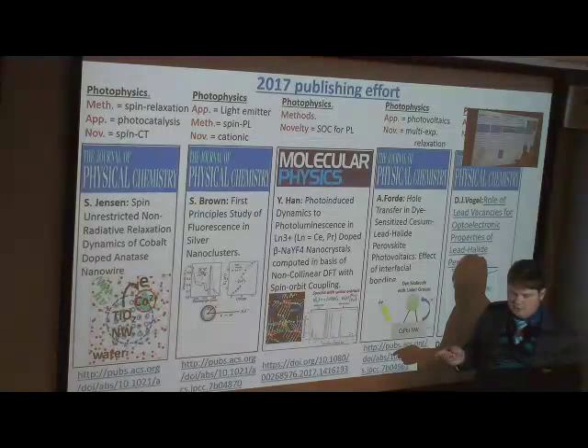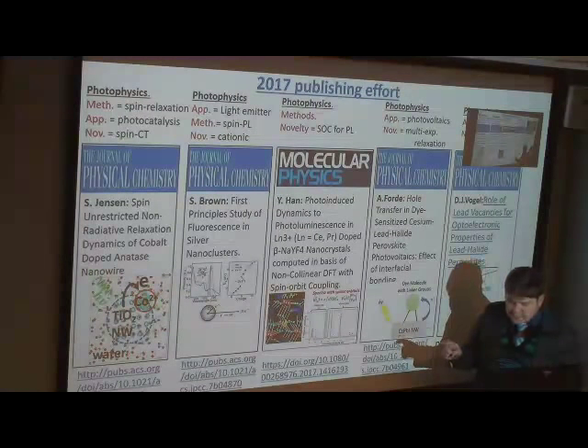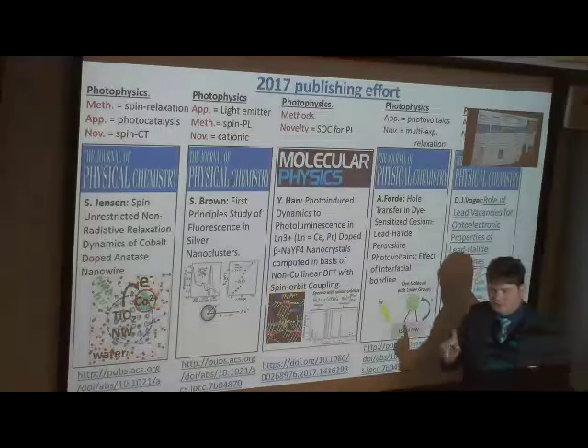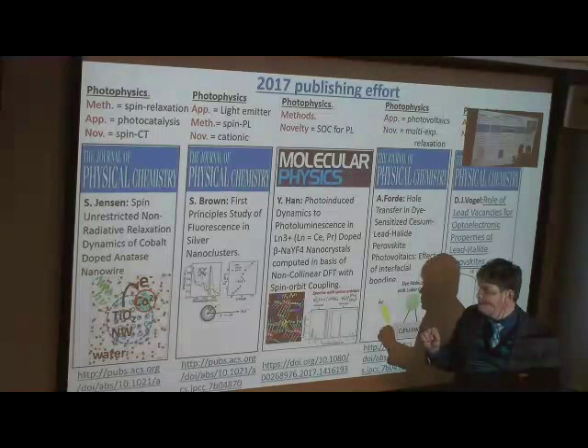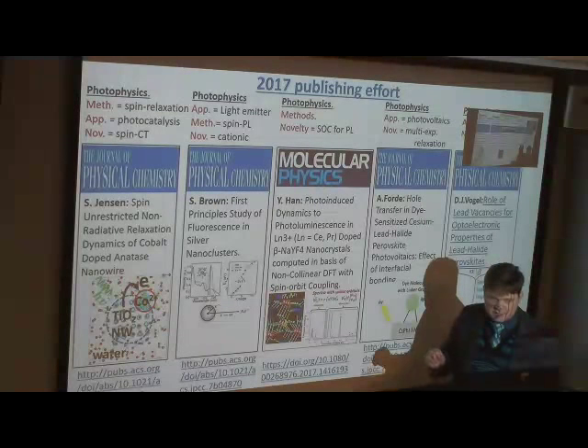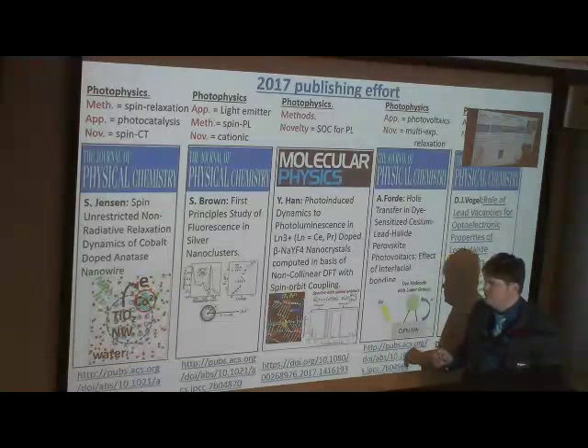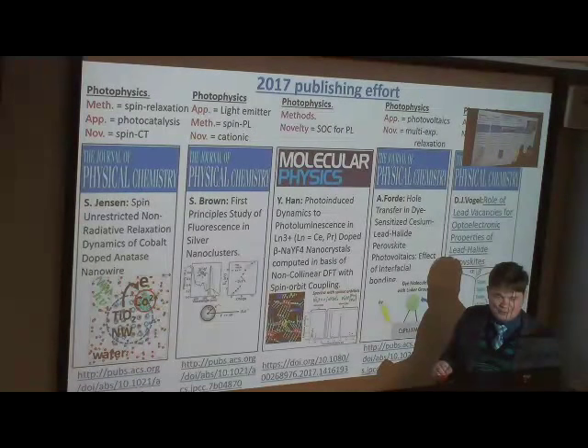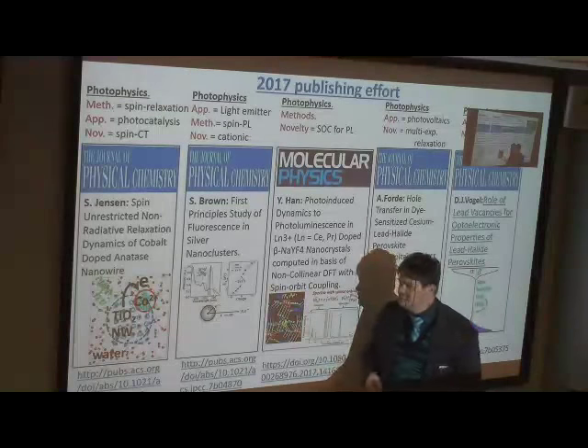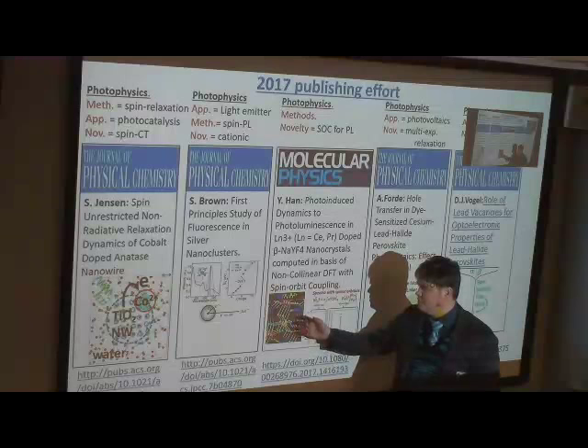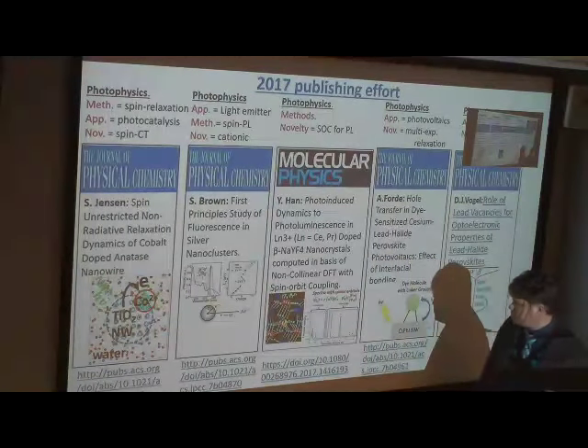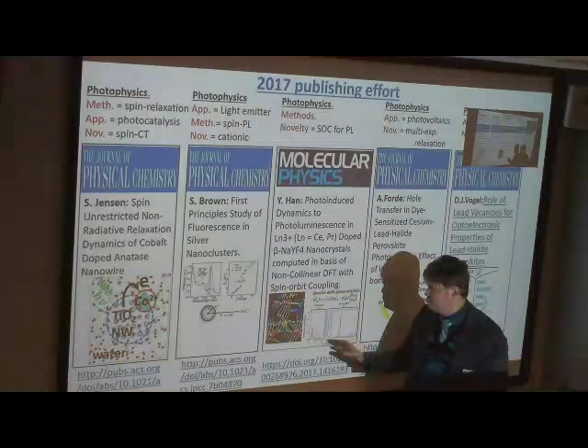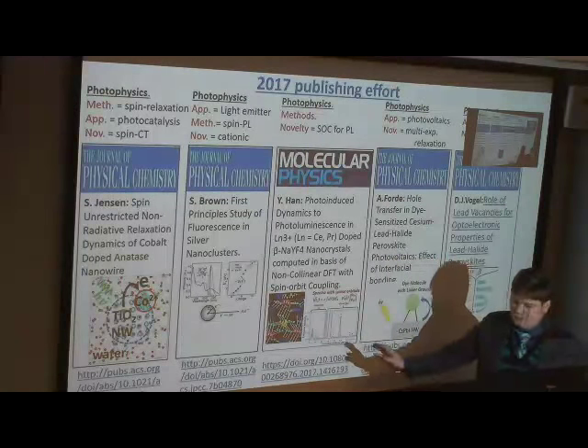There are superpositions of alpha and beta basis states of spin, and the expectation value of spin can be aligned not only along the quantization axis but in any arbitrary direction. This is the only basis where one can deal with spin orbit coupling. So this is the first paper that treats quantum relaxation of an excited state in the presence of spin orbit coupling, and it was tested on the example of lanthanide doping, which is a next level of complexity compared to transition metals, for praseodymium and cerium in transparent host matrices. It was also accompanied by computation of photoluminescence, which is the main application of these materials.